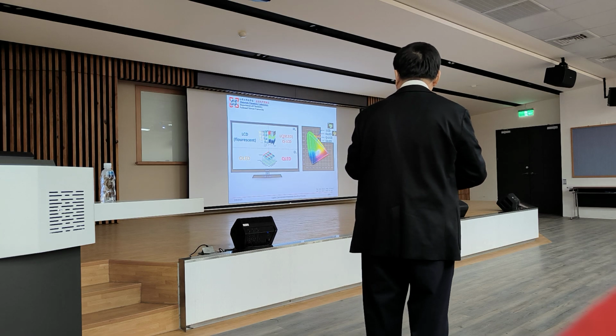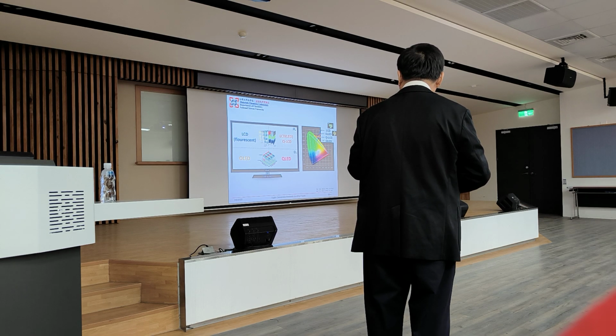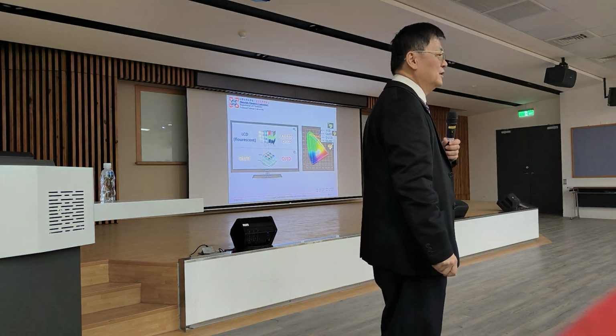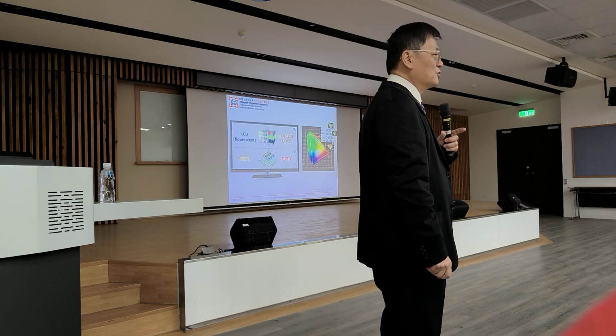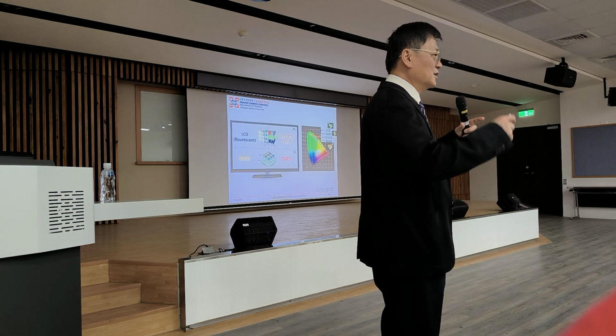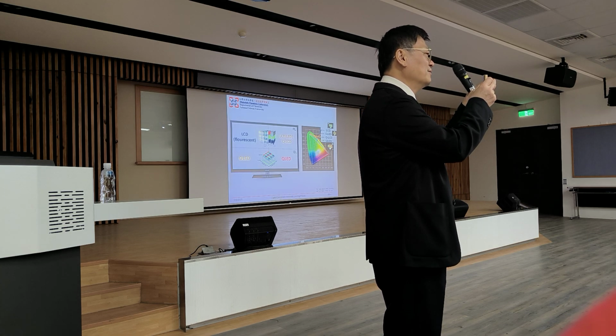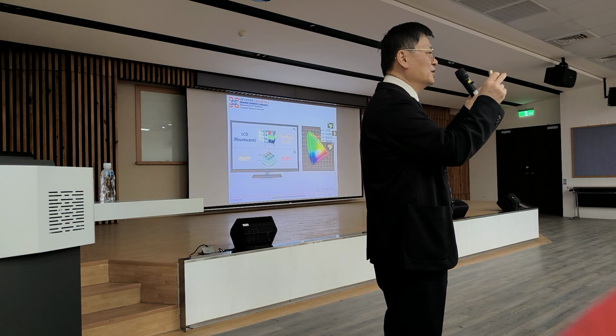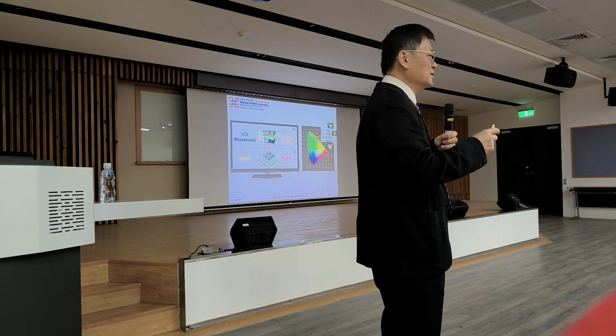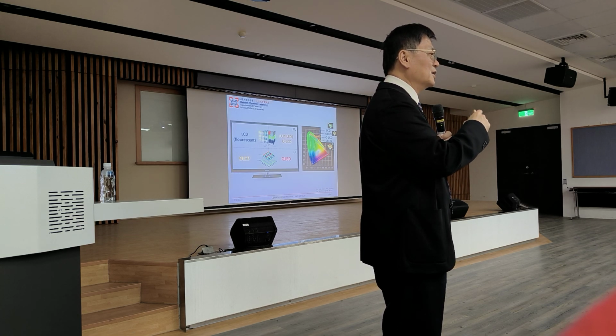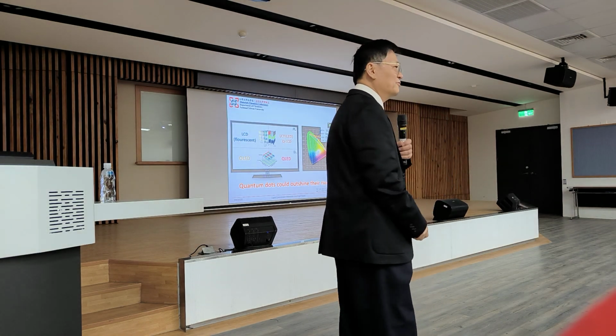Then you see, if you use a quantum dot film excited by a blue LED, this data is about 130. But if you use quantum dot as an emissive layer, this one is electroluminescence, the other one is photoluminescence. By using electroluminescence, you get up to about 140. Okay, so then you can see how good our quantum dot is. And why can it give such a large area? Because of the narrow band. Organic LED material has a full width at maximum of about 100 nanometers, but by using quantum dots, it can be less than 50 nanometers. So quantum dot becomes very important.